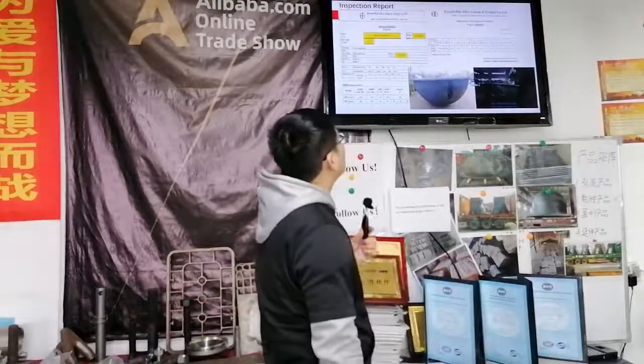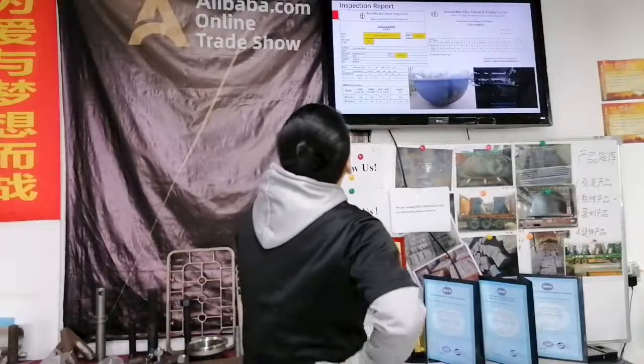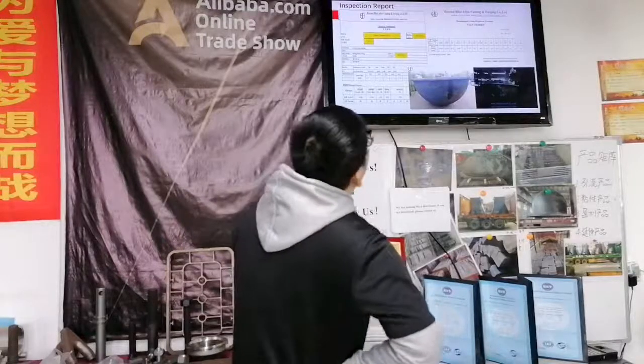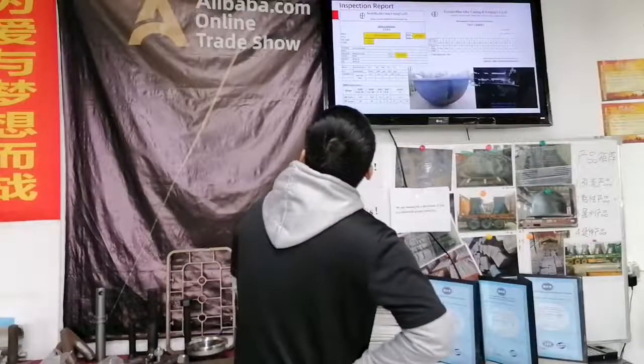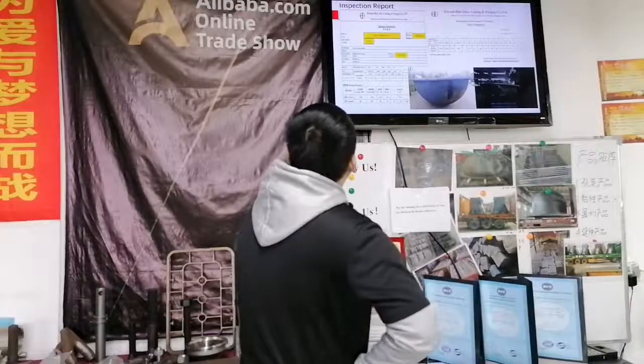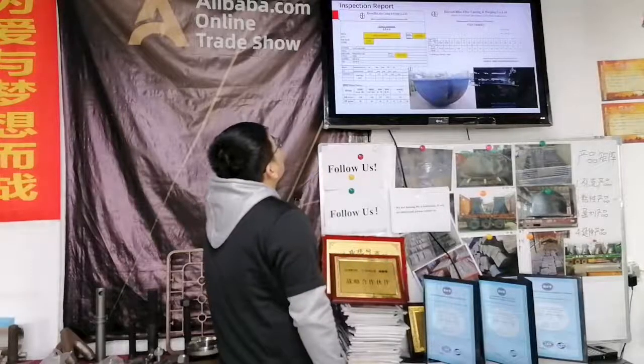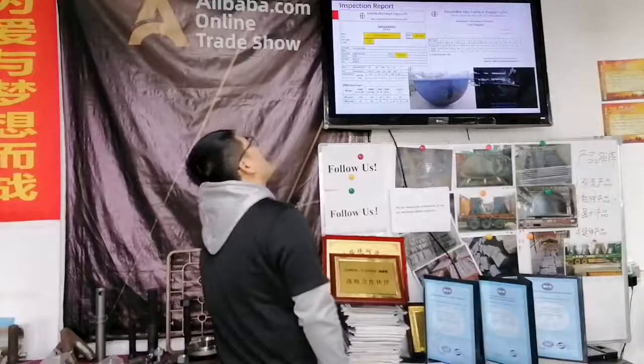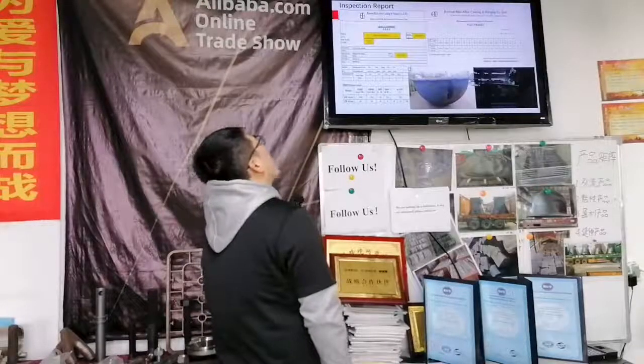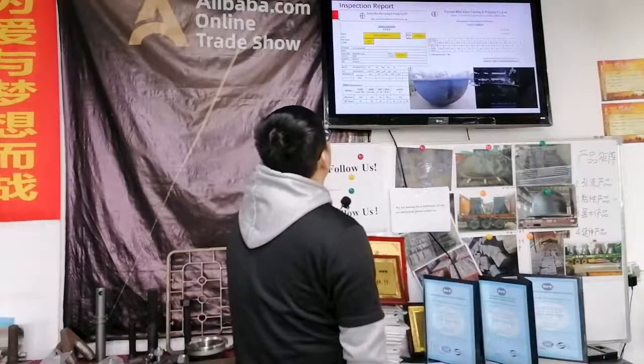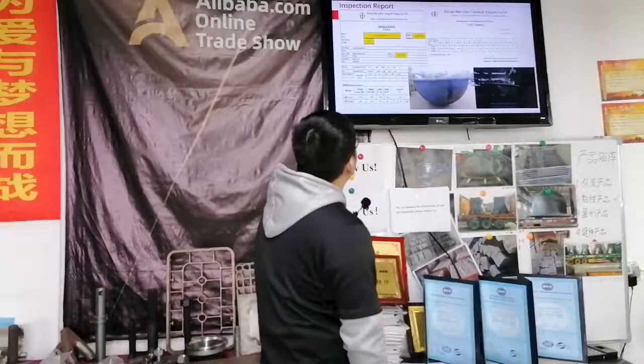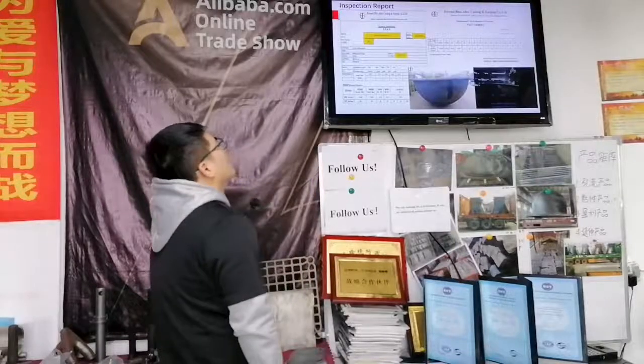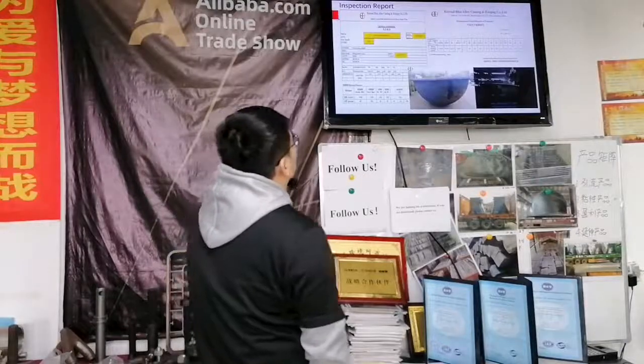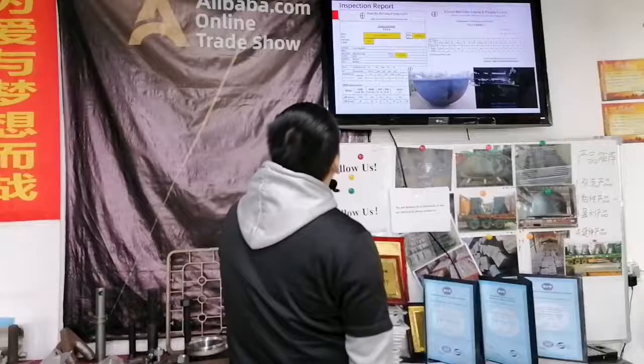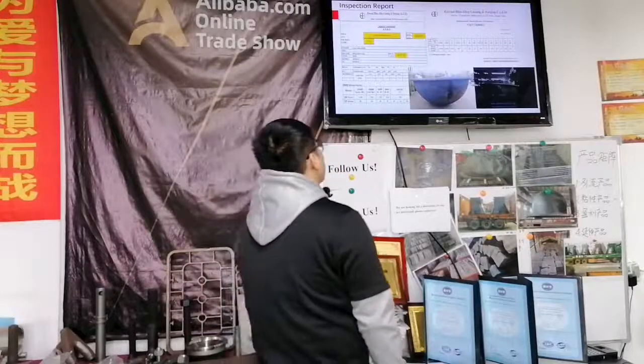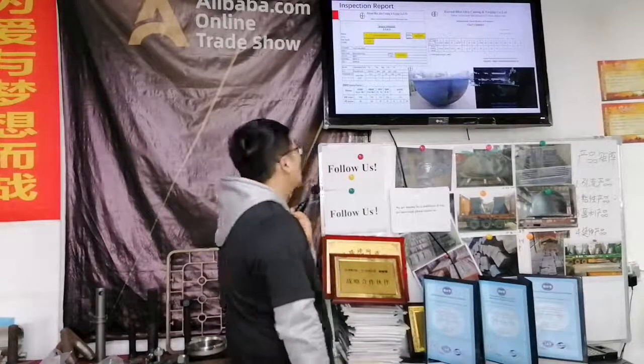And here is an inspection report which we produced last 2 years with 2 pieces. It's a small melting pot casting with 2 pieces. The chemical composition of the material, which uses BS 3104: the carbon is about 0.22%, under the control of the standard between 0.18 to 0.25. The silicon is about 0.33%, less than 0.6%.